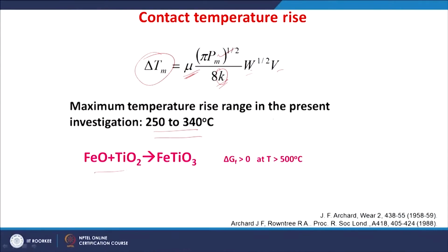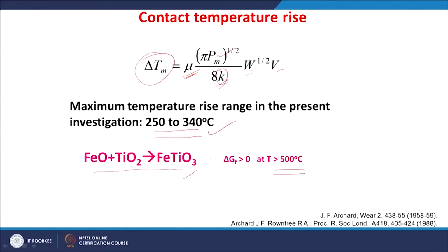So, again the thermodynamic data also show that such a reaction of iron oxide with the titanium oxide giving iron titanate is not feasible at a temperature more than 500 Celsius. So, it is an indirect indication that the temperature is less than 500 Celsius for the present investigated materials in the selected sliding wear contacts. So, this temperature also indicates the feasibility of this iron titanate.